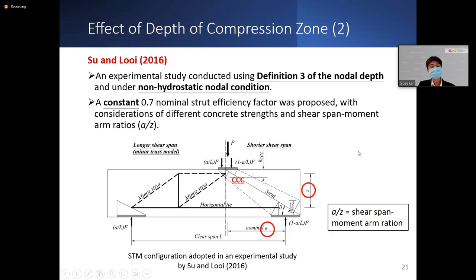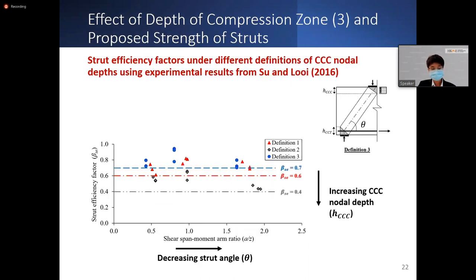I have investigated the effects of the three definitions of the nodal depth on the strut efficiency factor using the experimental results from Su and Looi. In fact, Su and Looi also used definition three and the non-hydrostatic nodal conditions, like here. They proposed a constant 0.7 strut efficiency factor with consideration of different concrete strengths and also the shear span to moment arm ratios. This figure shows the strut efficiency factors that I recalculated according to different definitions of the nodal depth against the shear span to moment arm ratios, which correspond to the decreasing strut angle theta here.